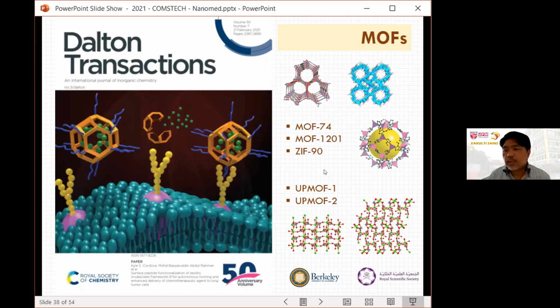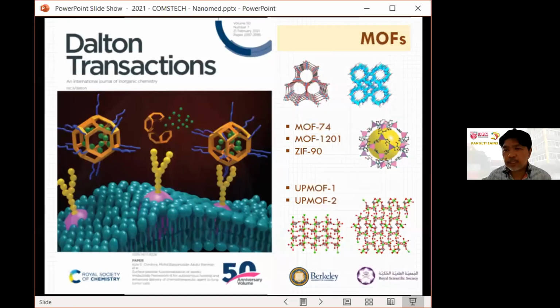And currently we are working with other different MOFs like MOF 74, MOF-1201 and ZIF 90. The beauty of ZIF 90 is that it has more places for the conjugation to take place. We are also working with our own MOFs, the UPM MOF 1 and 2, and the difference between all is that we are working on s-block metals, which are more biocompatible compared to the MOFs or ZIFs that have been used in most publications.